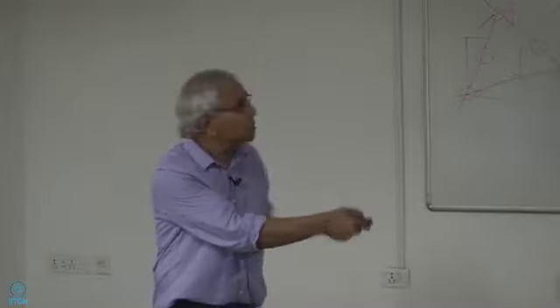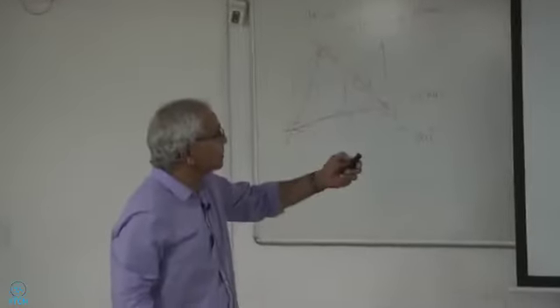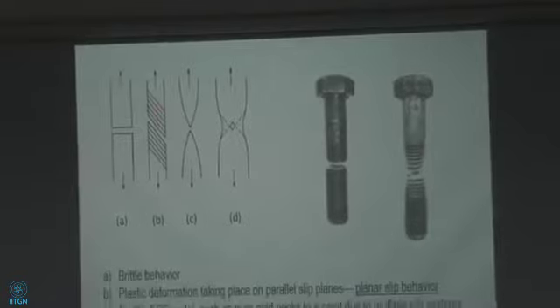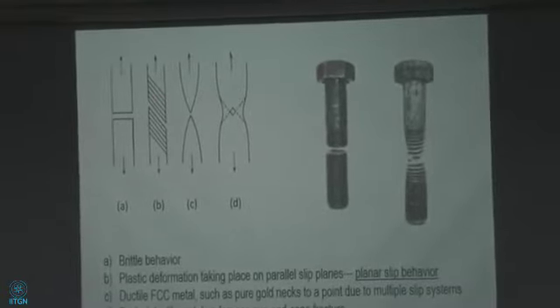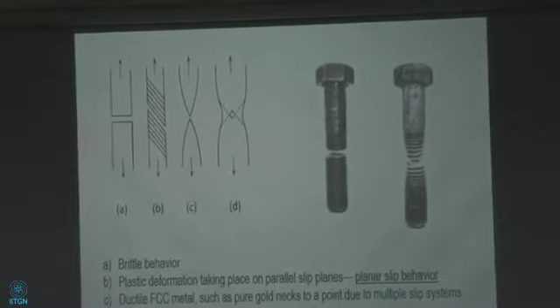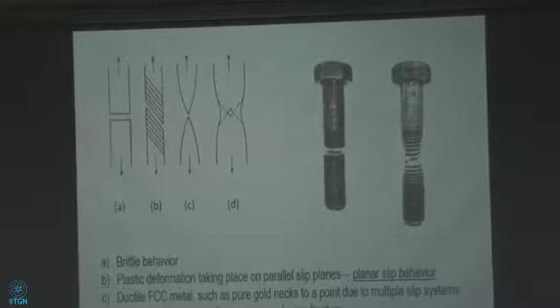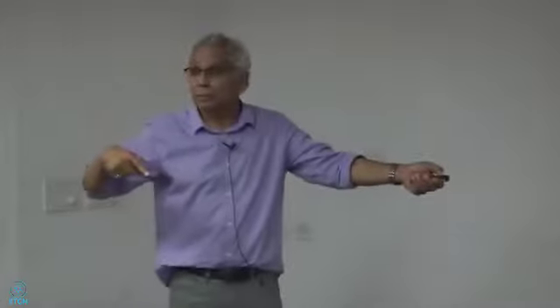When you have multiple slip systems acting, so I have this slip system and another slip system like this, right? Another slip system that is crisscrossing it. That means 2 slip systems are activated. You can have multiple systems activated. That is cross slip behavior. So this is planar slip. That is cross slip, multiple slip, cross slip.